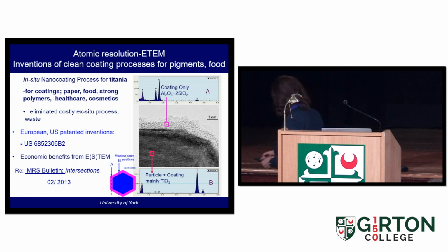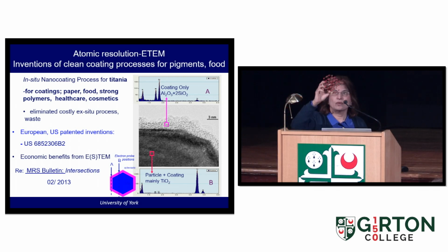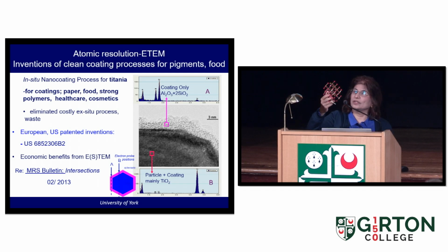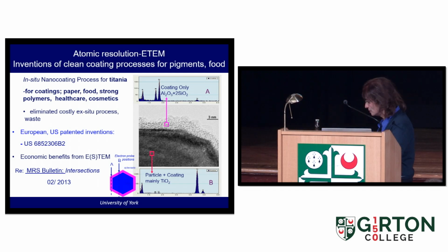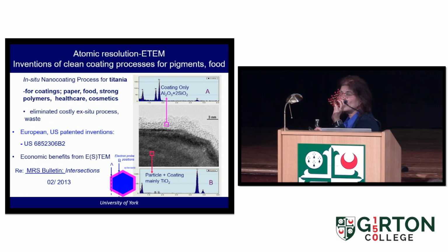And one is for titanium. And this is titanium structure here, titanium dioxide. You can see oxygen are the red ones and the yellow ones are titanium. And this is used universally in all these applications, as you can see here. Coatings, paper, foods, strong polymers, healthcare, and cosmetics. And healthcare, all the pills, they are white because it's got titanium in it. It's a non-toxic material, but it is very active under sunlight. So if you put it in the sunlight, it becomes gray, and nobody wants gray paper, right?